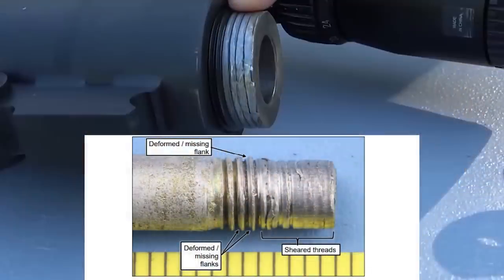Without diving too deep, let's just say that it is extremely rare to have a fatigue fracture that looks anything like the one we saw on Scott's gun. That look, on the other hand, perfectly matches that of stripped threads, where ductile shearing happened.